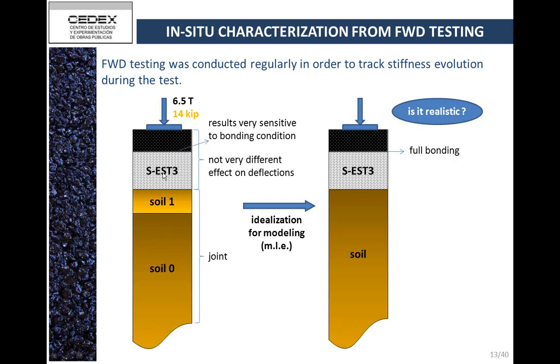But there were 2 additional problems. The first one is that here we have the asphalt layer, which is a stiff material, and here we have the cement stabilized layer. This comes from Spanish soil. This comes from estabilización, which is stabilization, and then 3. So this material is stiff. This material is also stiff. So it is quite difficult to distinguish the effect of this layer from this layer.